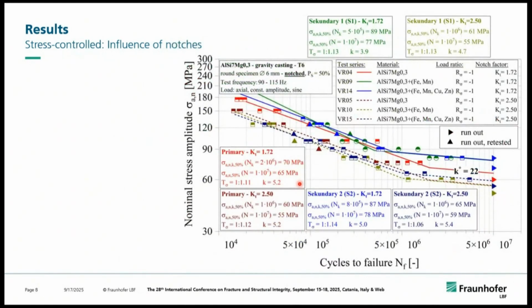The same result holds for the notch configuration. We have here in those 3 lines the results for the comparably smooth notch with a stress concentration factor of 1.72, and in relation to that, here the SN curves for a stress concentration of 2.5. We see at the end that notches are equalizers of fatigue strength and material strength. Not really something surprising when we compare the unnotched specimens and go over to the notched configuration.